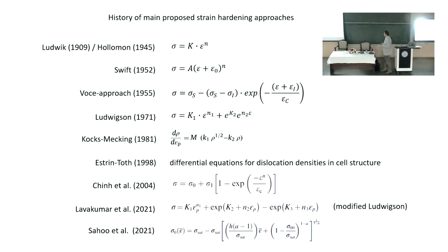And then came the basic research in which strain hardening is described with the help of dislocation densities. We know that the most responsible part of material strength of metals is dislocation density. So if there is only one general dislocation density, not like two phases, then dislocation density variation with strain can be described with the help of a so-called factor here, and then rho is dislocation density.